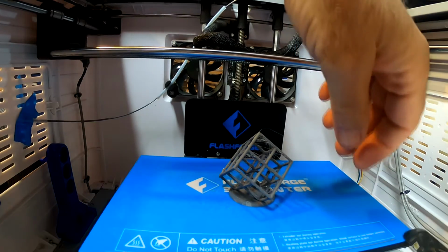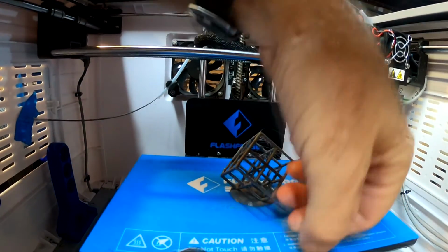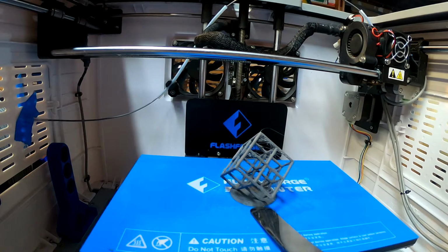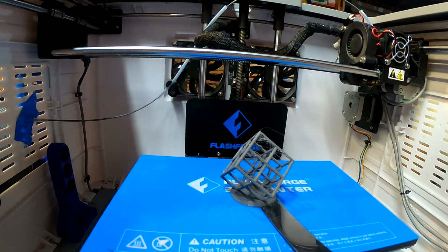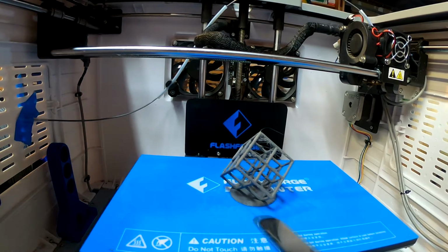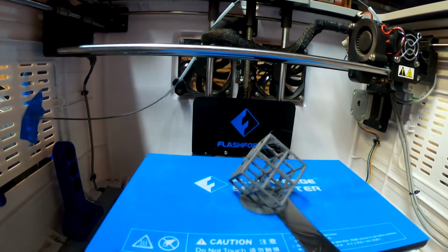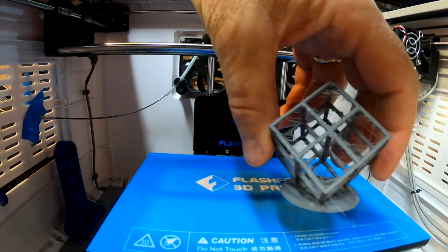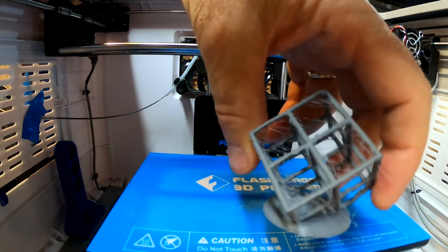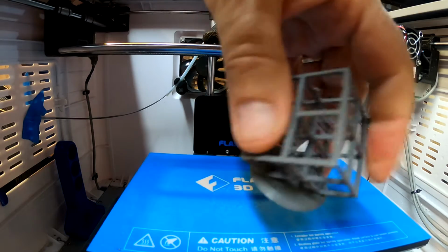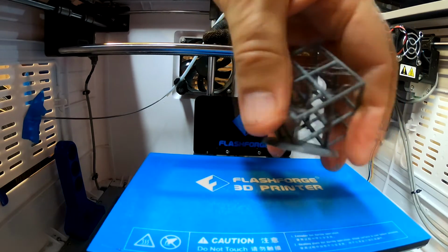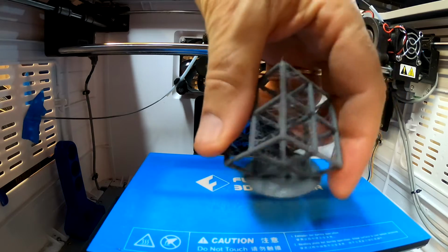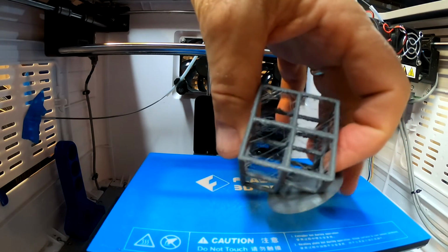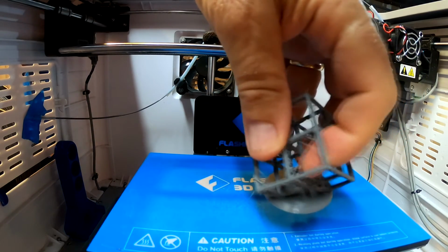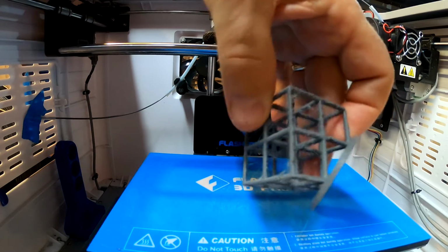All right, it's done. So it printed okay, but it looks like it has lots of stringing, so I guess we're going to have to do a retraction test. Okay. Still got really good hard bed adhesion. A little bit easier. So maybe we need to go down to 30. Did we do 30? Put up another 5 degrees. So lots of stringing. Pretty okay, and the strength is good. Can't crush it. So we're going to be doing some retraction tests to get rid of this stringing. Alright, that's our next test.